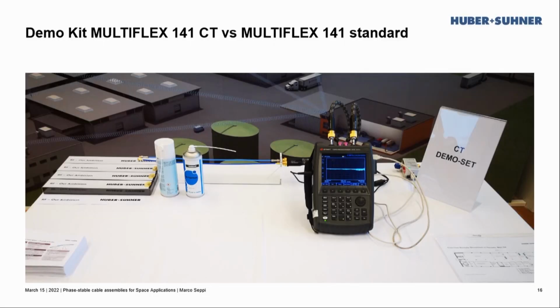We don't get only stability, we get superior insertion loss performance, and we offer that with a flexible material which is easy to handle and easy to mount in different conditions. Below you can see some of these characteristics. As you see, through foaming we can reach a level of porosity between 30 and 60%, a low relative density of the dielectric, and the dielectric constant down to 1.4, 1.6, which is an excellent result and can bring us to a temperature service of 200 degrees and a frequency operation up to 67 gigahertz. Very high also for different applications that we have.